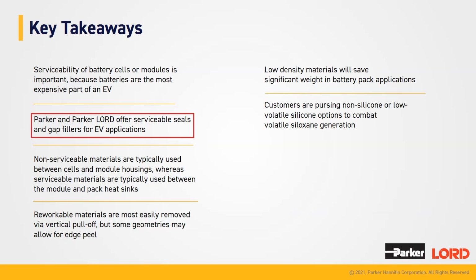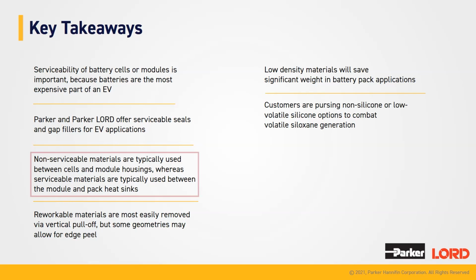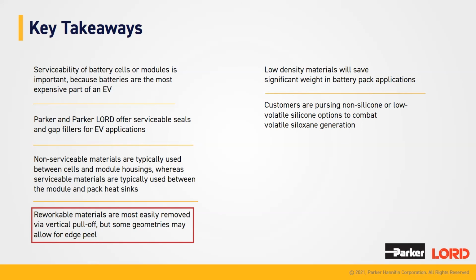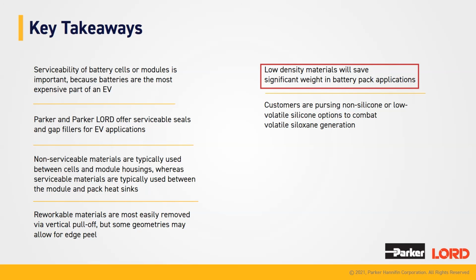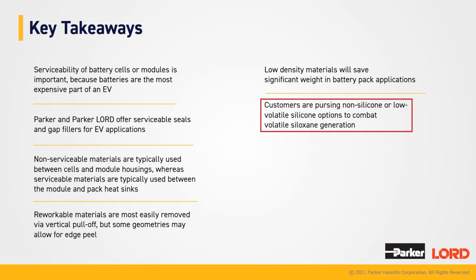The second takeaway is that Parker and Parker Lord offer serviceable seals and gap fillers for EV applications. Thirdly, non-serviceable materials are typically used between cells and module housings, whereas serviceable materials are typically used between the module and the pack heatsink. Next, reworkable materials are most easily removed via vertical pull-off, but some geometries may allow for edge peel, which could reduce the overall pull-off stress. Fifth, low-density materials will save significant weight in a battery pack application. And finally, we frequently see customers pursuing non-silicone or low volatile silicone options to combat volatile siloxane generation.